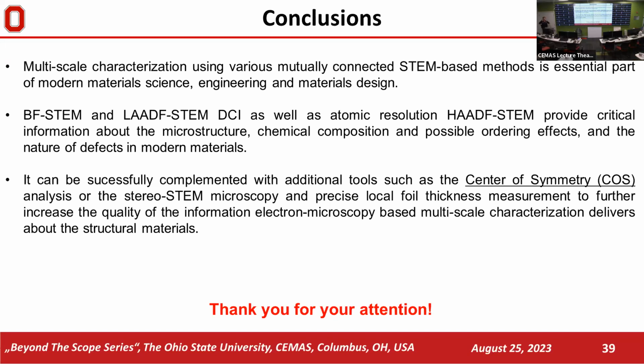But for that, when I was showing the COS and the distribution of different stacking sequences and positions of partials, fortunately we were able to validate it using just tilting experiments and looking at the defect from the side and doing different G's and the ribbon fringes. So we have that validated for this specific case. Obviously, it took a lot of work hours, but there are also cases where it didn't fit together in terms of COS. So yeah, I agree. One has to be careful. Yeah, thank you.